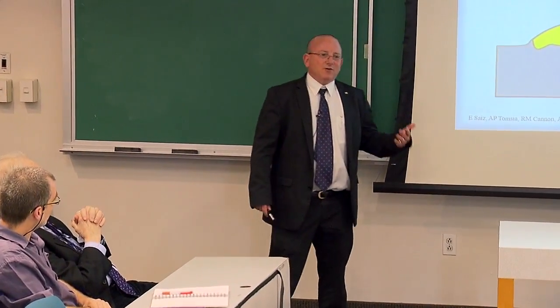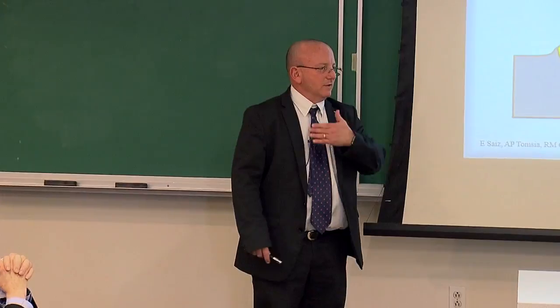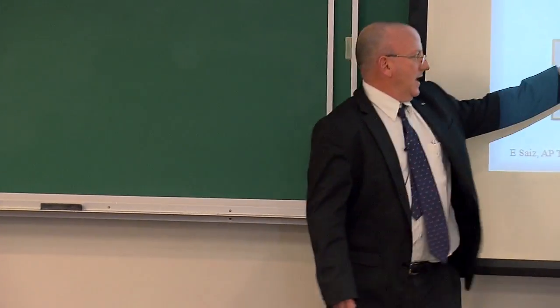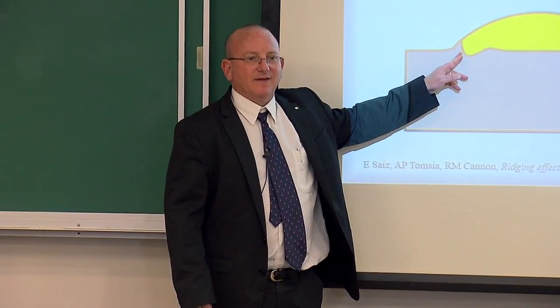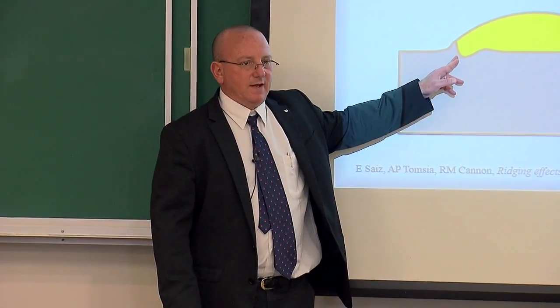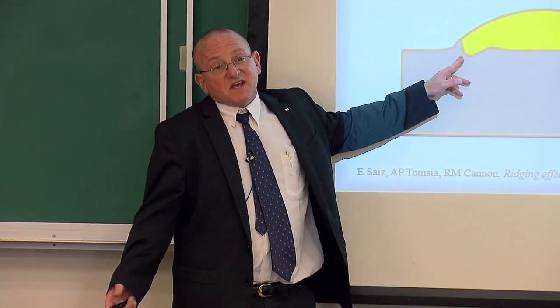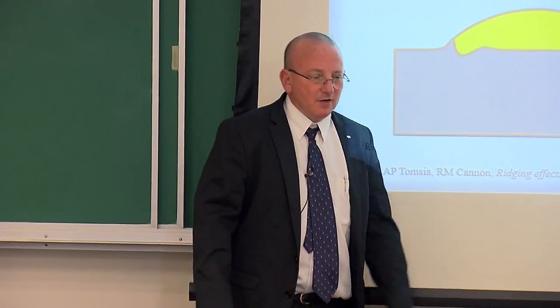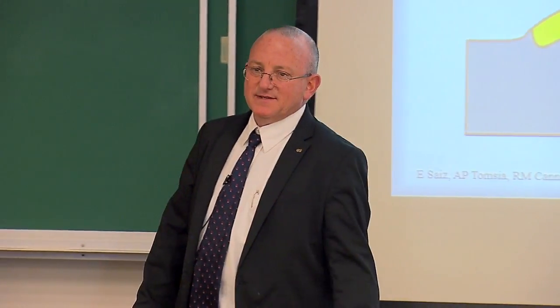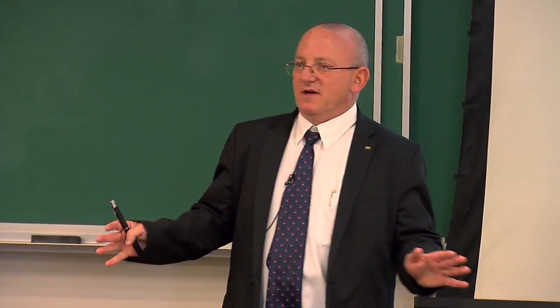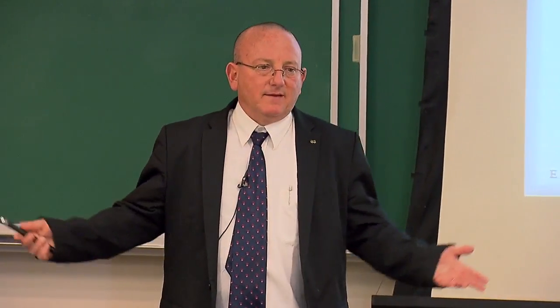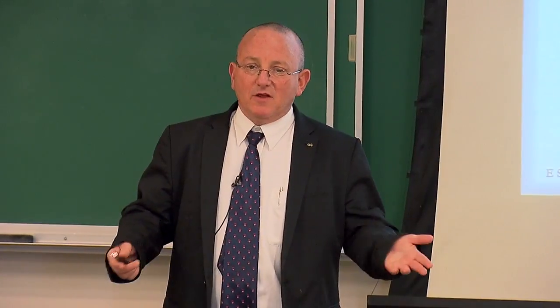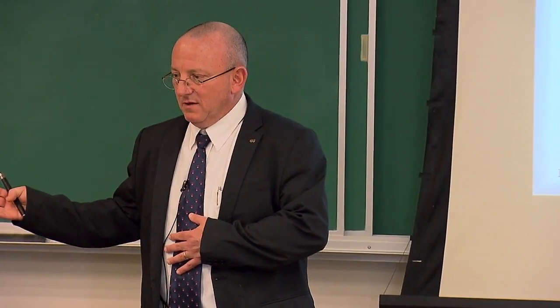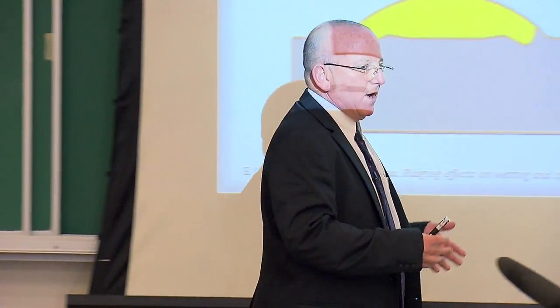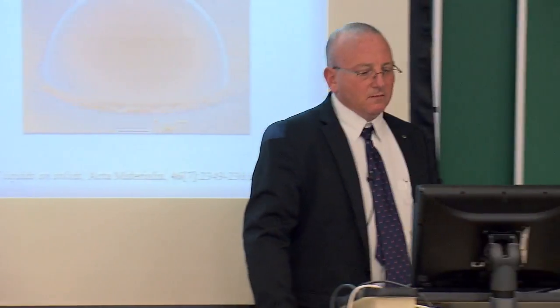So technically what we need to do every time is to get rid of the liquid, look underneath it, look at the shape, and look at the real contact angles and try to deal with them quantitatively. Or say, okay, I'm not going to do that. I'm going to look at a drop of water on a piece of glass, and I'm going to measure within 5 minutes, and I'm going to be honest with myself, and I won't call this an equilibrium contact angle. But the 5 minutes is going to be relevant for whatever process that I'm interested in. And if I want to do a comparison in that way, that's almost kosher.